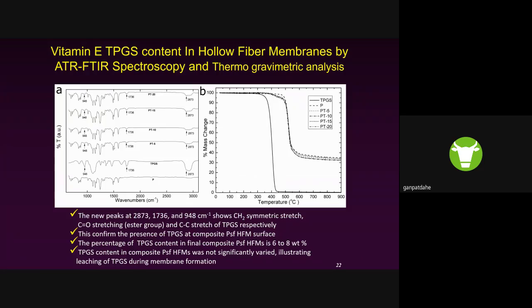It's very important to confirm the presence of the vitamin E in the polymer, that hollow fiber composite. So we first conducted an ATR-FTIR study, and from this study we found some new peak formation at these wave numbers, and from this it confirmed the presence of the TPGS.